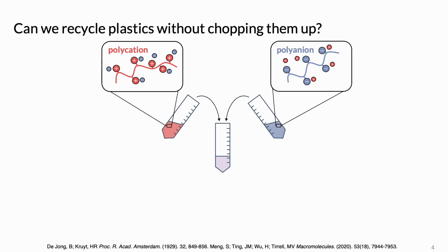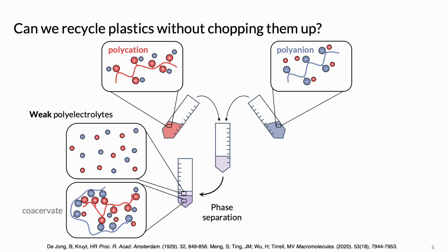For example, if the polycation has a positive charge that goes away with change in pH, then we categorize this as a weak polyelectrolyte. It's weak because the charge groups aren't always charged, and so it can't always attract a negative charge. And when we mix two oppositely charged weak polyelectrolytes together, parts of the polyelectrolyte chain will not be able to ionically pair with a long-chain molecule of the opposite charge, as shown in the diagram, where the two chains aren't fully touching. This means there's more room for salt or water between chains, and the chains don't tangle well enough to give the resulting material strength.